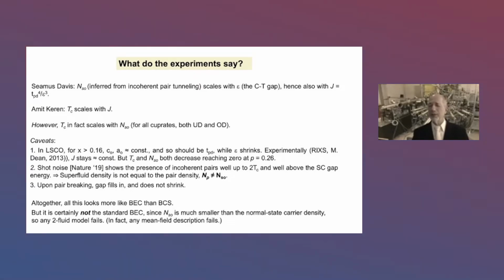Now, what do experiments say about this U and J? Well, Seamus Davis showed a beautiful experiment where he was using STM, scanning tunneling microscope with a superconducting tip, and was monitoring the pair tunneling. It was incoherent pair tunneling, not Josephson tunneling. And he inferred from that somehow the superfluid carrier density, and also from the spectroscopy inferred the value of the charge transfer gap. And then he found that the superfluid carrier density determined this way scales with the charge transfer gap, and therefore it should scale with J.